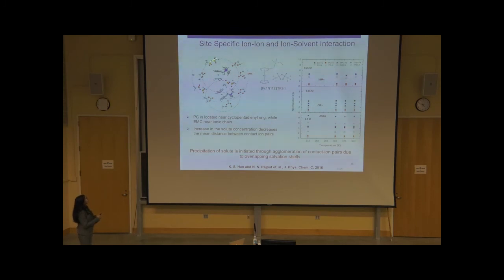We also found some site-specific ion-ion and ion-solvent interactions, where some solvent molecules have a preference to sit close to the cyclopentadienyl ring of ferrocene, and some solvents, such as EMC, like to sit close to this ionic liquid chain. And as we increase the concentration of the salt, at 0.25 molar, we form solvent-separated ion pairs, and at 1.7 molar, we form aggregates in the solution. And experimentally, we found that this is pretty much where we are reaching the solubility limit.